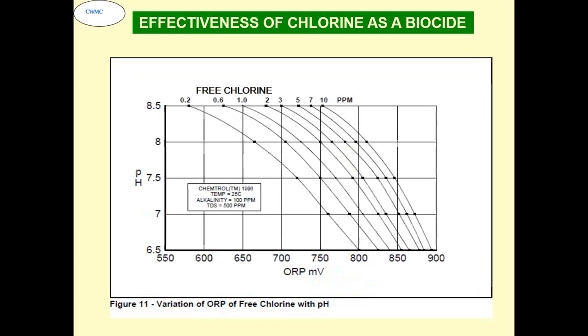Okay. If we look at it, there is a correlation with the ORP, oxidation reduction potential, which is the potential generated when the system is in equilibrium. So there is an oxidizing reaction and a reduction reaction. That ORP measurement is a tool which can give you a direct indication of the effectiveness of the biocide.